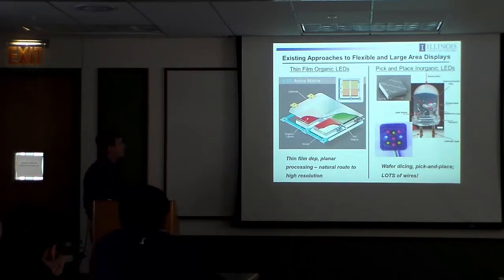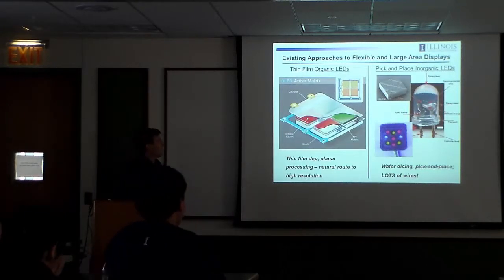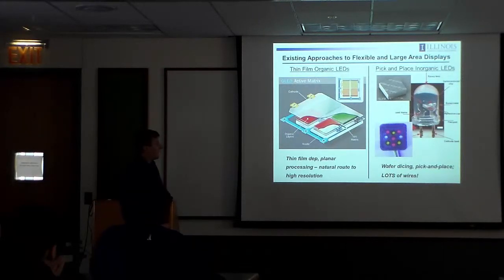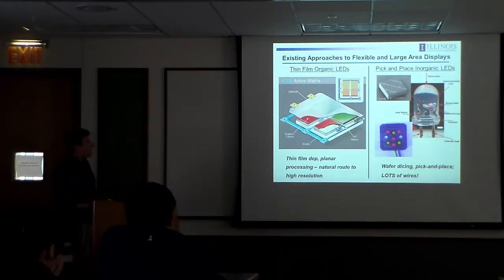So the upshot is that this kind of inorganic LED technology begins to look a lot like organic LEDs in the sense that they're very thin, they're compatible with planar processing, and you can develop large-scale arrays of them on a planar substrate. And that's a lot different than what you can do with LEDs today, where you dice up the wafer, you end up with these big chunky blocks, and then you move those around with a robot, you put them in cans, and then you do wire bonding to form pairs of terminals to each individual device, and then you take those things and you tile them up and you make giant macro scale displays, but in a way that does not downscale in size or upscale in number of pixel elements very easily.